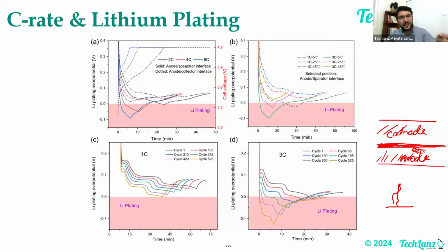In constant CCCV charging, the current is very continuous, so there is a continuous potential difference. You're giving a very high current for a long period of time, and this was at 4C. But even if you're giving 6C charging, if you're giving an intermediate gap, what happens in this intermediate time is the ions have time to diffuse.